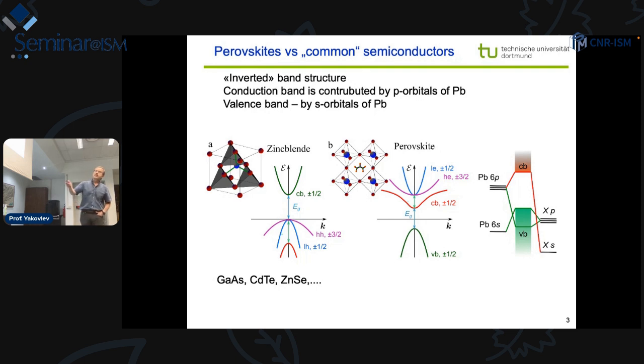If we go here to the perovskites, we take these bands and it looks like we flip them over, but they also push out these complications of the holes. It's now the heavy and light hole bands, but they split off by very large energies, about 1.2 to 1.5 eV spin-orbit interaction. So what we are left with is simple bands, which is very good and very easy for making spin physics in its ultimate appearance.